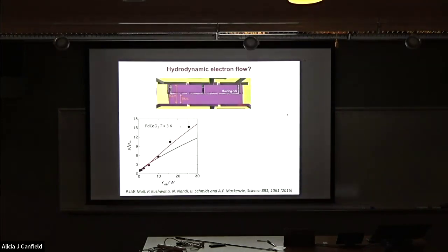Now, one of the first things that we did when we were doing these kind of experiments was to study how the resistivity or the flow resistance of a bar changed as we changed its width. And what we saw in 2016 was that if we made the measurements, we got data looking like the black dots. And if we analyzed them with what turned out to be a flawed model, we would say that if you were purely ballistic, you would get something like the blue line. If you allowed yourself a small hydrodynamic correction to that, so you included what's called momentum conserving scattering in your theory, then you would get the red line, which matched the data much better than the blue line.